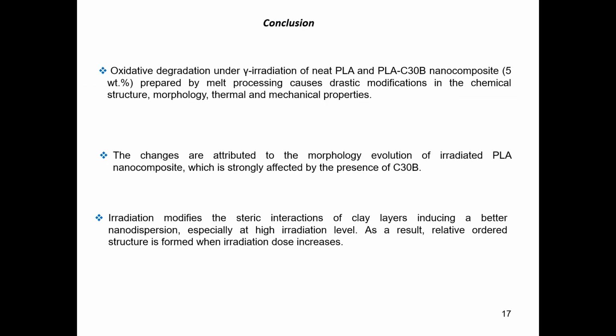In conclusion, oxidative degradation under gamma irradiation of neat PLA and PLA-based nanocomposite prepared by melt processing causes drastic modifications in the chemical structure, the morphology, and the thermal and the mechanical properties. The changes are attributed to the morphology evolution of the irradiated PLA nanocomposite, which is strongly affected by the presence of C30B. Irradiation modifies the steric interactions of clay layers, inducing a better nanodispersion, especially at high irradiation level. As a result, a relatively ordered structure is formed when irradiation dose increases.